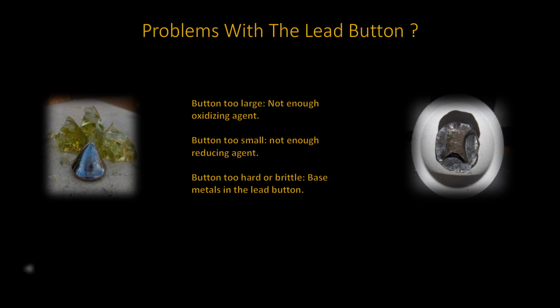As already mentioned, the weight of the lead button should be about 28 grams, more or less. If your lead button weighs greater than 30 grams, you would need to increase the amount of oxidizing agent, that is niter, to inhibit the creation of the lead, especially when your ore is a reducing ore. If the ore was a class 3 ore, then you would need to reduce the amount of reducing agent. That would be the quantity of flour used.